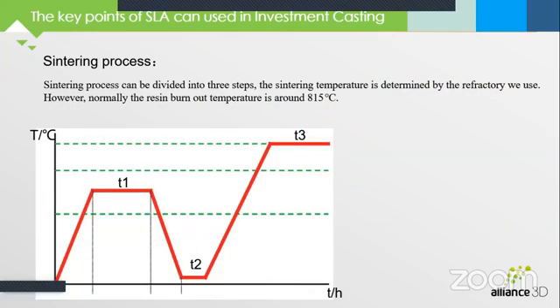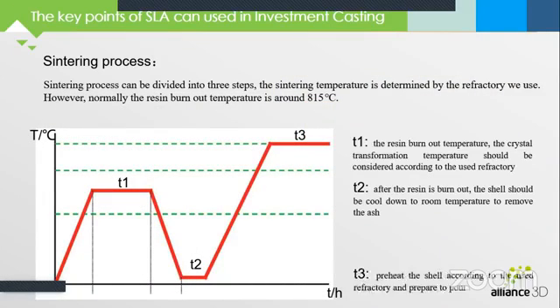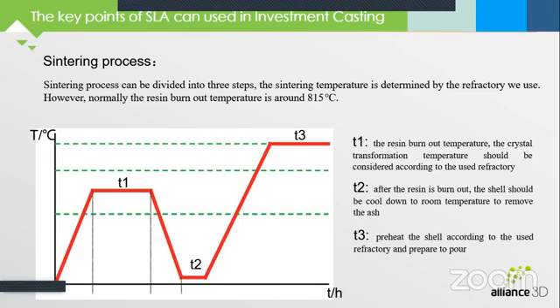The sintering process. The sintering process can be divided into 3 steps. The sintering temperature is determined by the refractory we use. However, normally the resin burnout temperature is around 815 degrees. t1, the resin burnout temperature and the crystal transformation temperature should be considered according to the refractory used. t2, after the resin is burned out, the shell should be cooled down to room temperature to remove the ash inside.